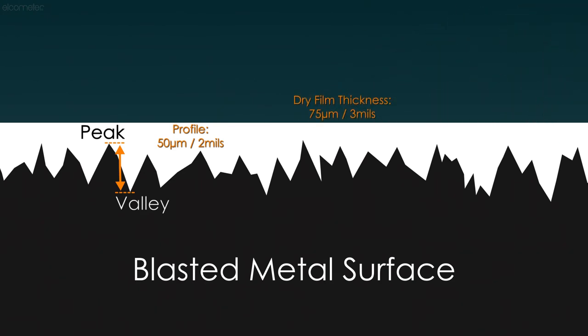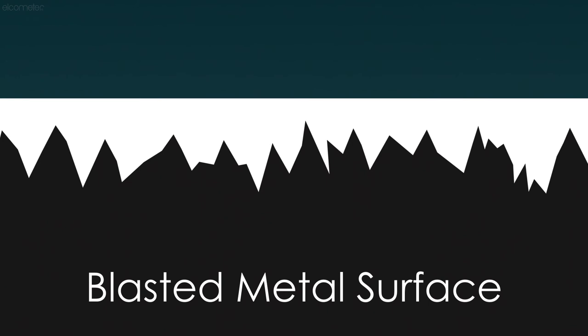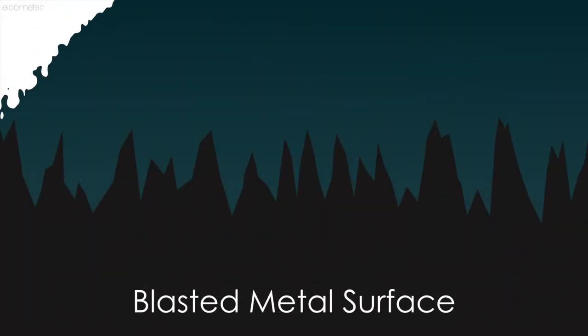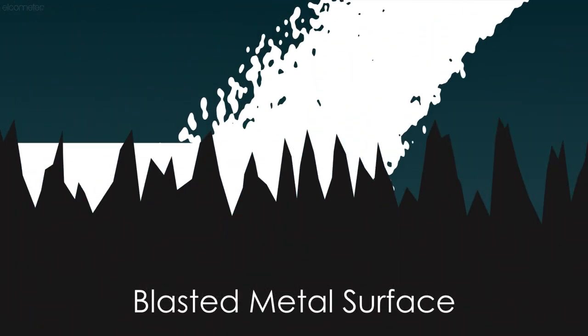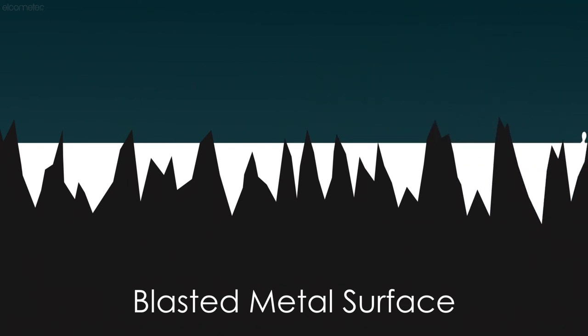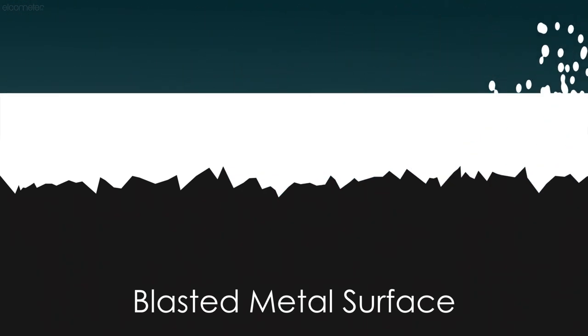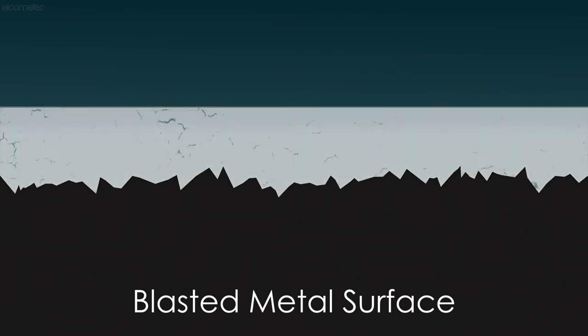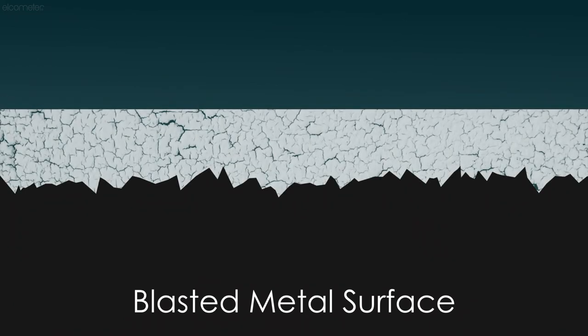The key here is that the required coating thickness is applied to both the valleys and the peaks, otherwise you get rust spots. So if the profile is too high, the amount of paint used to cover the peaks is significantly more, otherwise there are thin areas of cover, resulting in poor protective properties, leading to rust rash and early failure. If the profile is too low, then the coating applied can be too thick, leading to possible cracking of the coating whilst it dries or cures, resulting in corrosion and pinholes.